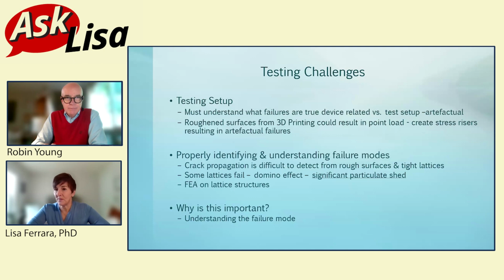You've got roughened surfaces on the titanium, especially when they first came out, they were doing EBM and laser, but those roughened surfaces weren't as perfected at that point, and trying to identify cracking. So as you all know, for interbody cages, we run static and dynamic compression, compression shear, torsion. Well, you have to inspect, and we always did.